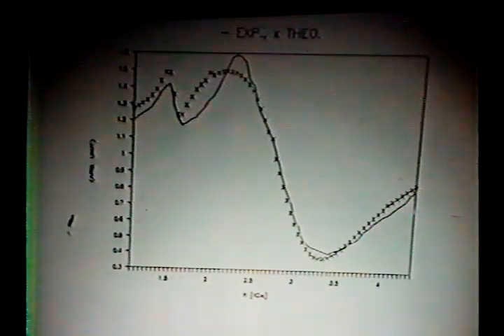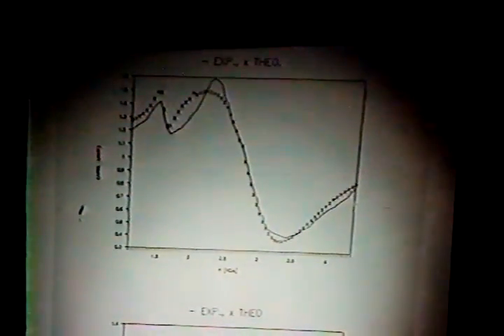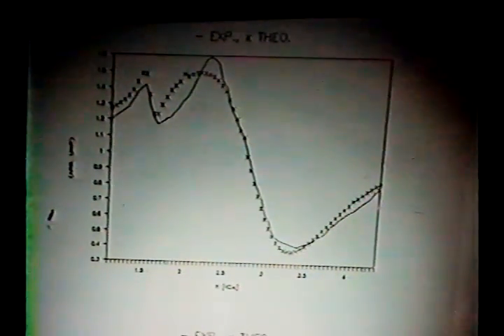What's happening here is that the magnetic moments that are in this, they're not flipping anymore. They're frozen out at low temperature. So the Hamiltonian that describes the super paramagnetic phenomena is just not working. It's no longer super paramagnetic at low temperature. And the reason for that is there are anisotropies. That means that you have to add other terms in there we haven't added in, like the size of the particles and the shape of the particles. All those things have to be added to the Hamiltonian. And that's very difficult to do. So that's why the agreement here is pretty bad. And it's one of the things we're trying to work on right now. So that's ferromagnetic resonance.